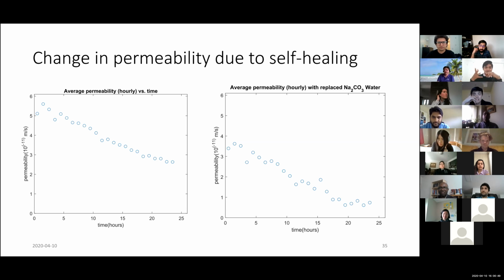But after leaving the samples under that water for 7 days, I did observe a different color of the samples, as well as some precipitation outside the sample itself. There was some powder that I could detect, but it did not precipitate in bulk amounts inside the water. So there wasn't anything at the bottom of the pond, for example? No, there was nothing at the bottom of the pond. I'm just concerned about atmospheric precipitation, and whether we are losing any sodium carbonate into the atmosphere, or getting reacted. To tackle that, I usually cover them. All the samples are kept in the steel box, so there is no evaporation of water happening once the samples are inside.